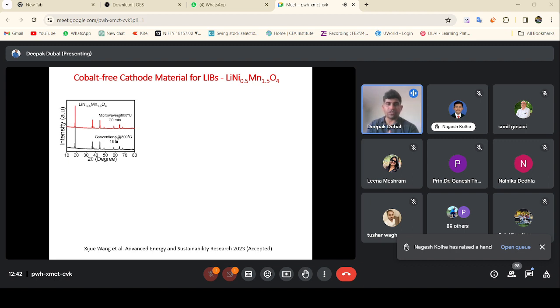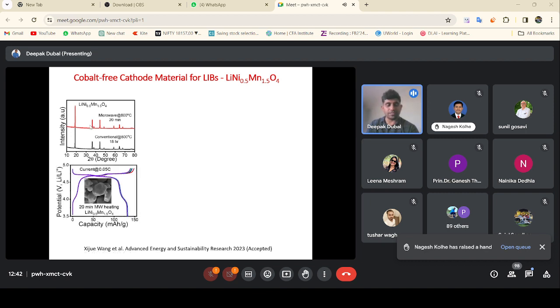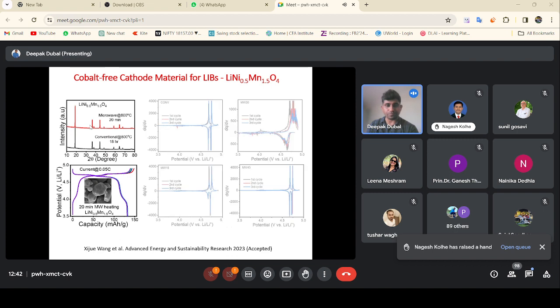And you can see here the X-ray diffraction I just put here to show you the conventional method, 800 degrees Celsius for 18 hours, and we synthesized the same material using microwave at 800 degrees Celsius in only 20 minutes. So you can see there is no difference in the structure of the material. At the same time, we tested the material for a lithium-ion battery, and we get a specific capacity which is very, very close to the theoretical specific capacity.